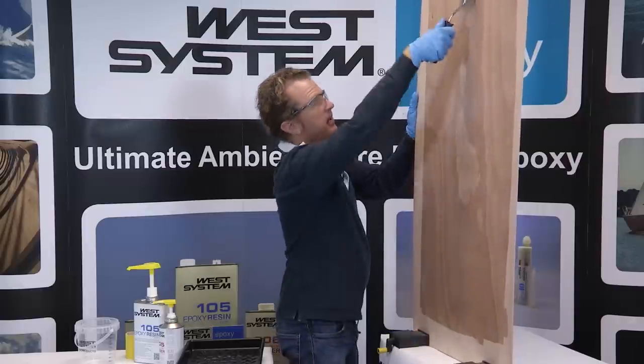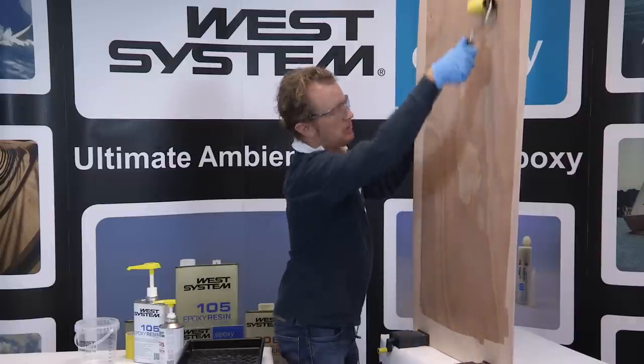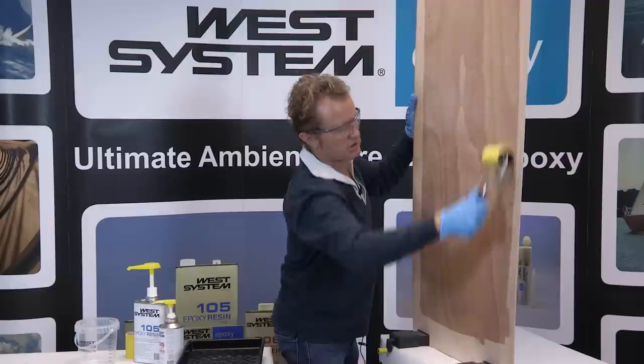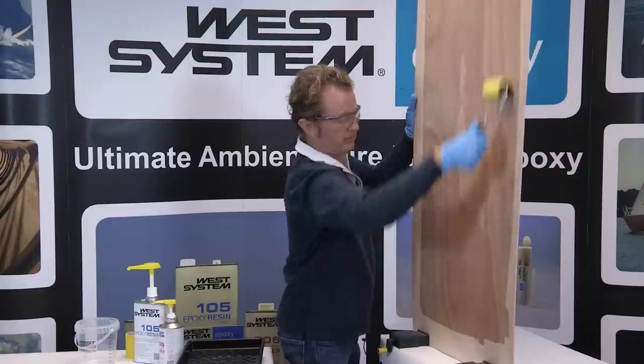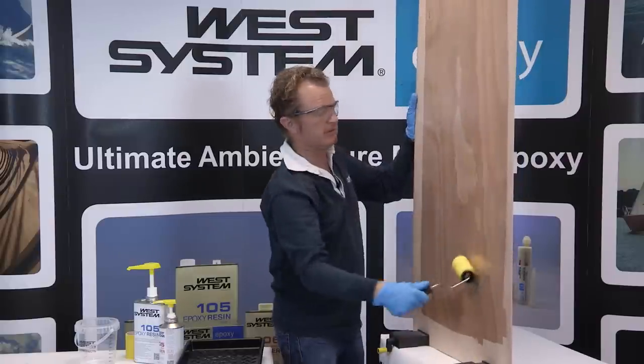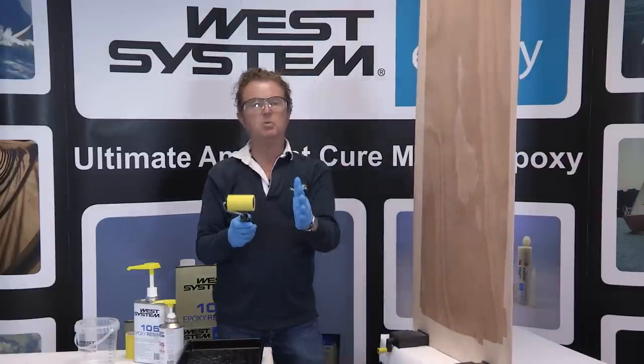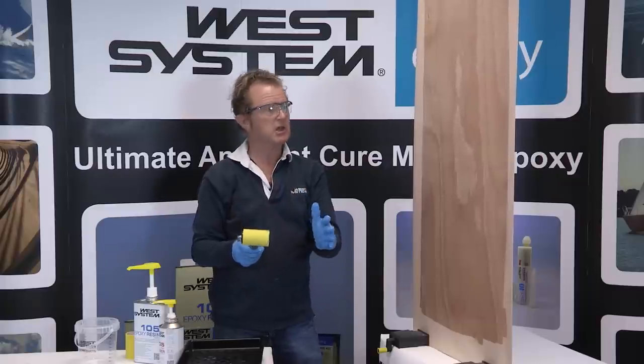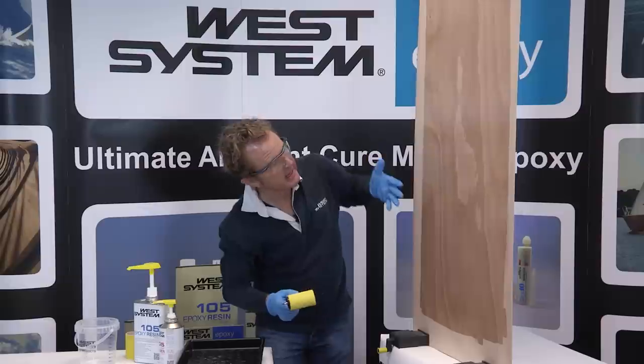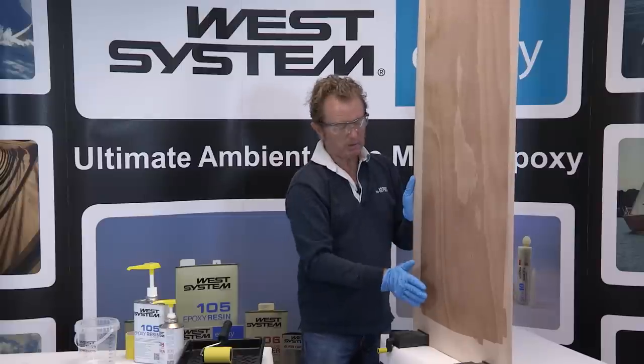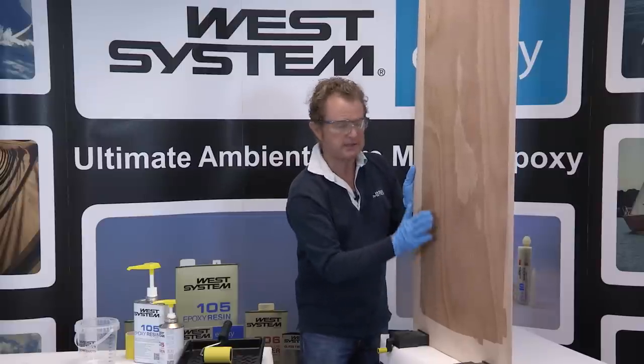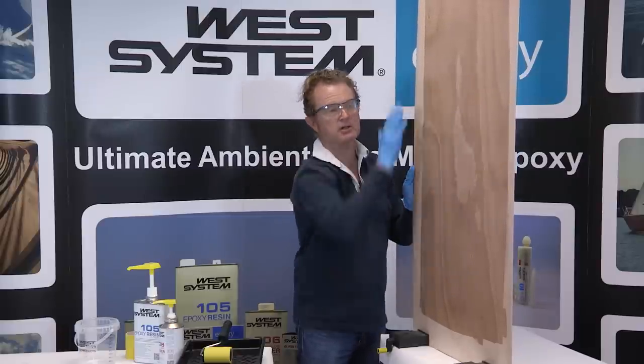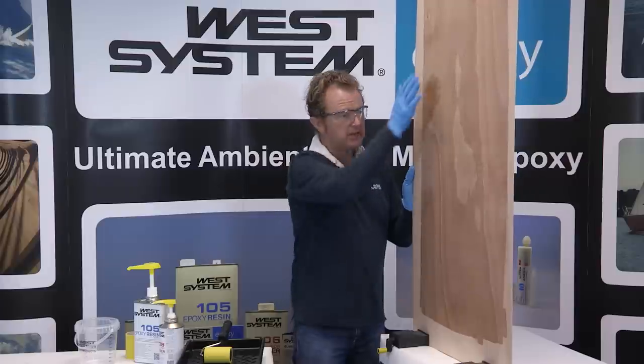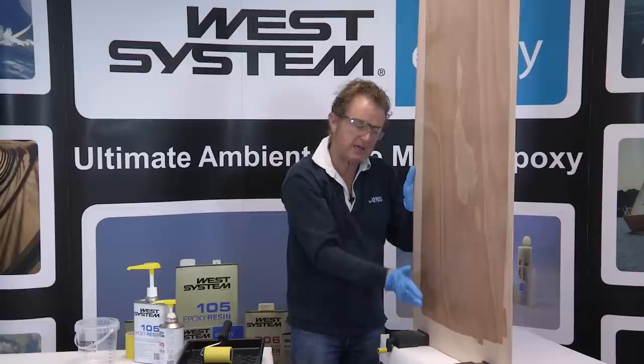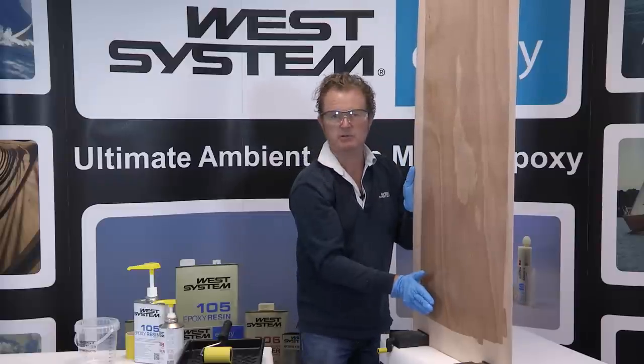Just making sure that I make a final pass with my roller just to distribute the epoxy nice and evenly. These rollers are available in a wider width for larger surface areas, but you can see how quickly and how evenly I've distributed the epoxy. This is really important because if you flooded areas of the surface with excess epoxy, then when you apply the glass, it will have a tendency to float on those areas.